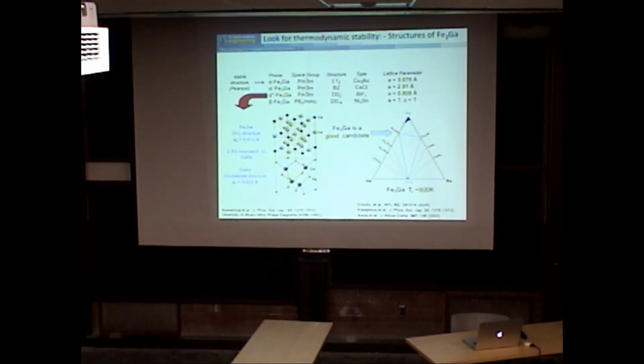Okay. So that was us saying we can grow iron, it works, we can spin inject from it, it all works well, but you'd like something that's thermodynamically stable. So what I actually point out here is, if I look at this ternary phase diagram, this tie line suggests that Fe3Ga should be stable on gallium arsenide. That's what the thermodynamics is telling you. So what we try to do then is say the normal phase, if you look at the iron gallium phase diagram at room temperature, is this one.